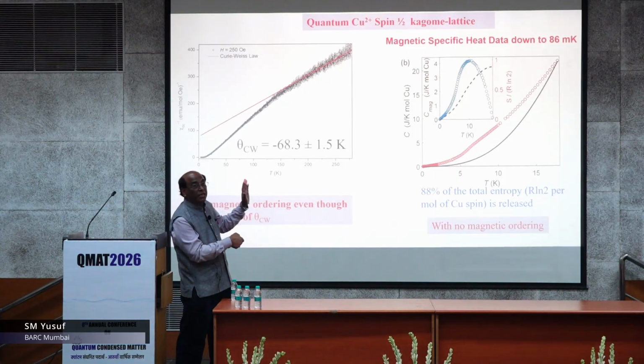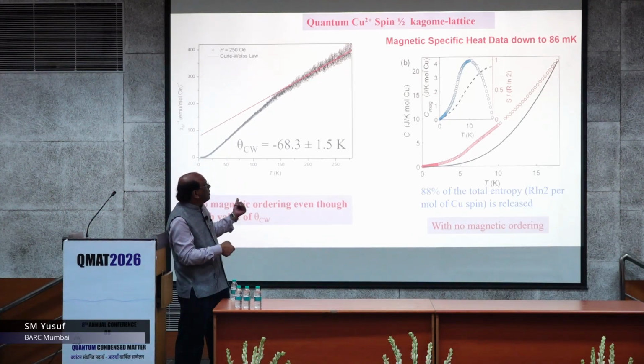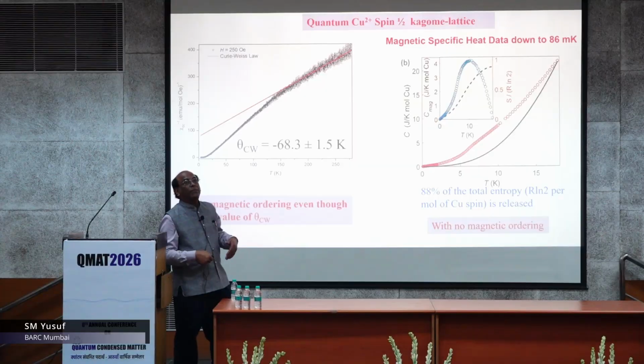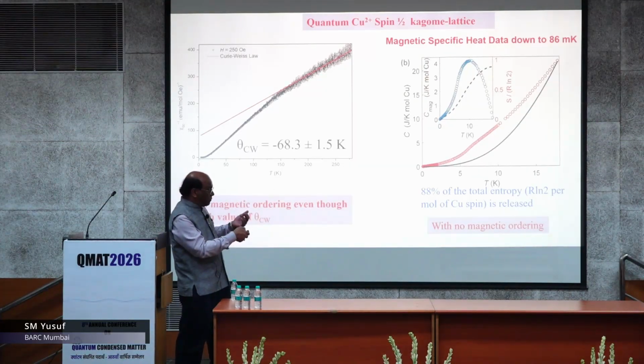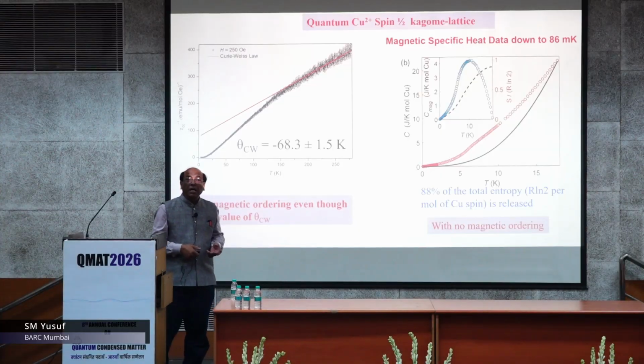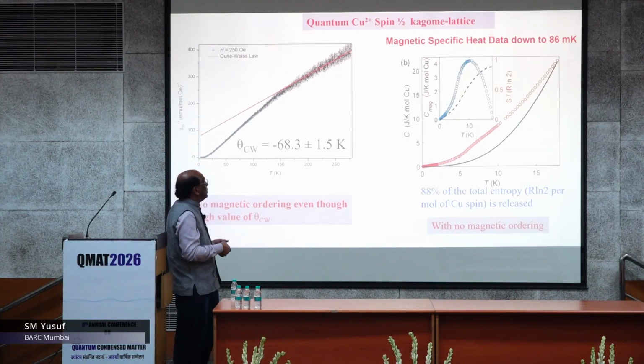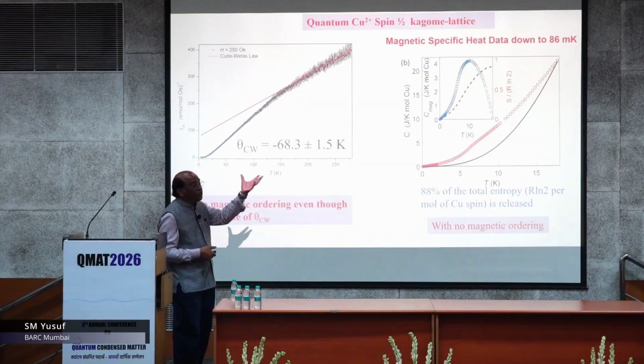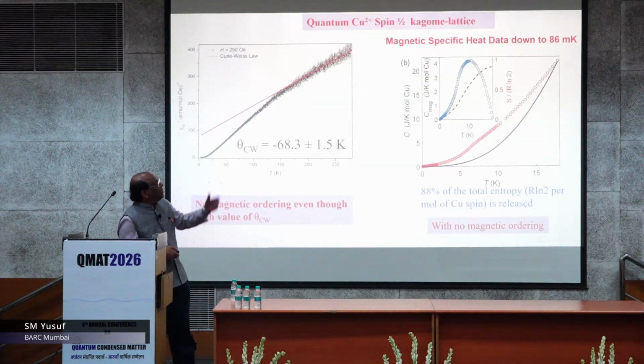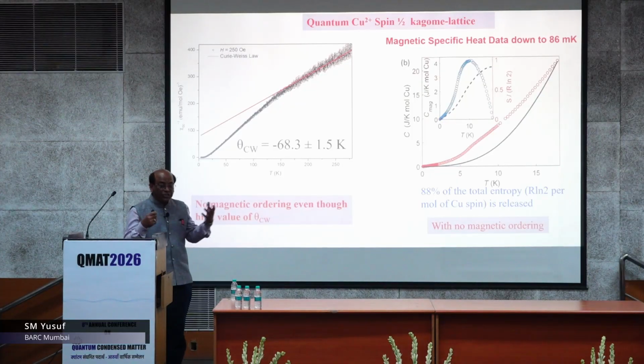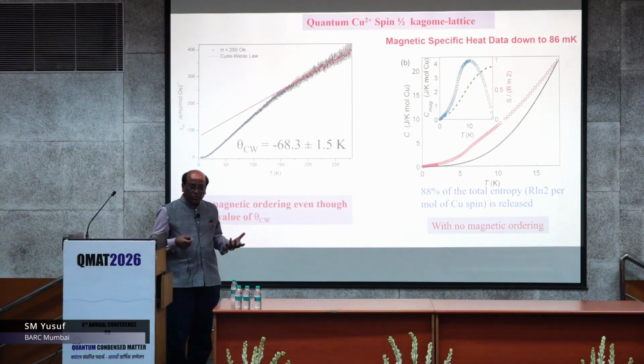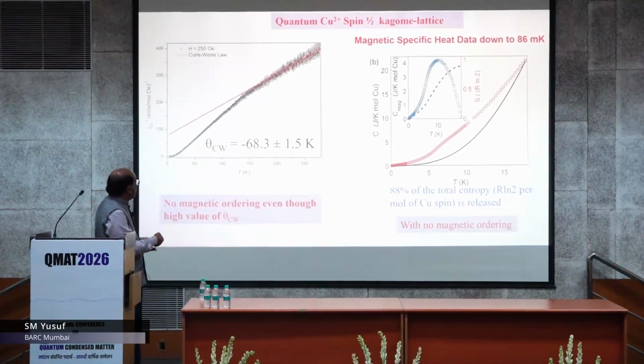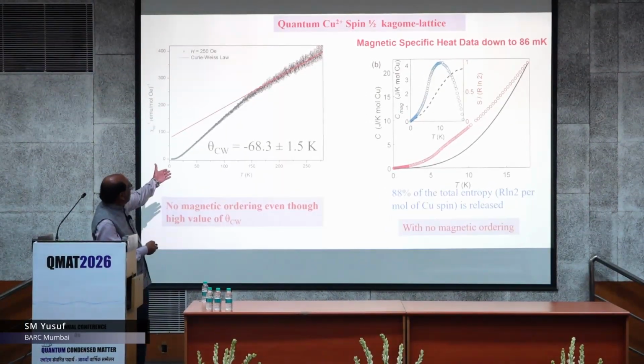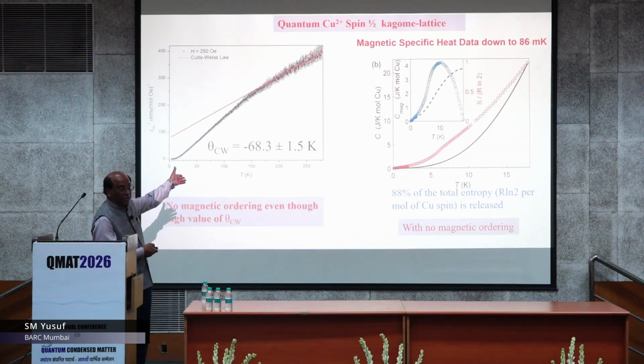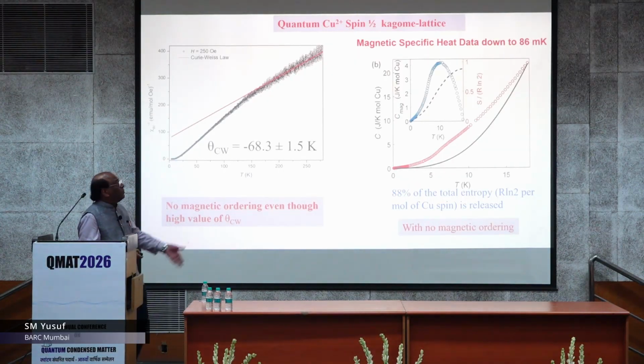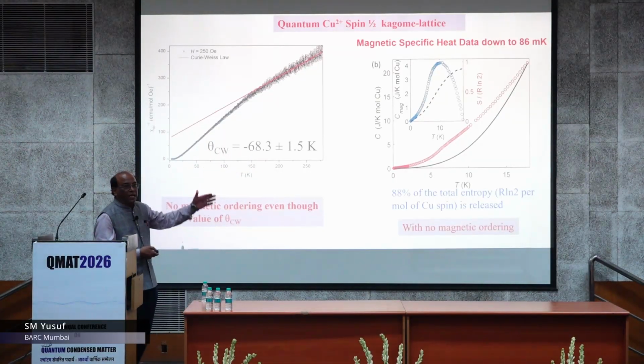but there is no phase transition, magnetic phase transition, and putting it another way, only 12% entropy is left to have any phase transition if it is feasible below 86 millikelvin, and that is very, very unlikely, because 12% entropy cannot lead to yet another magnetic phase transition. So this kind of residual entropy left at this kind of very, very low temperature is a clear-cut signature of zero point quantum fluctuation and quantum properties of this kind of fascinating system, and a very large theta value without Tn. So here if you define the F factor, it is infinity, because no ordering. Or even if you put 86 for argument's sake, then you see what is the value of that F factor.